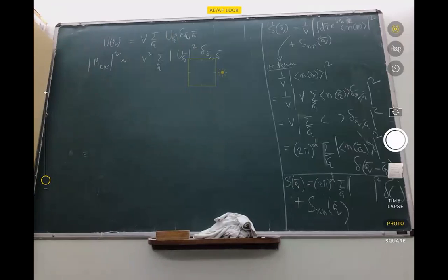Okay, now here is the answer to your question. Saurabh, you had asked me why the reciprocal lattice vectors are important. So one thing is that you saw that we can classify and designate families of lattice planes using these reciprocal lattice vectors. But here is another place where it shows up. In scattering experiments, you have scatterings only when Q is one of the G's. So any arbitrary momentum transfer is not possible in a periodic system.